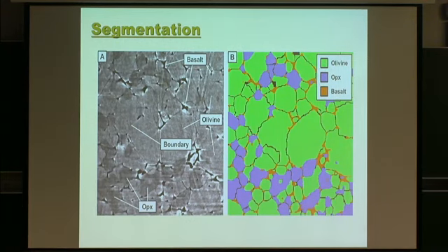And so here shows how we do the segmentation and ground truthing. All right, so the one thing is that the X-ray is going to have a really hard time detecting the grain boundary, because there isn't much of a difference between them for you to detect. So the grain boundary usually is really hard. So in that, we have to rely on some program to interpret that it's olivine. So there can be uncertainties in that grain size, all right?